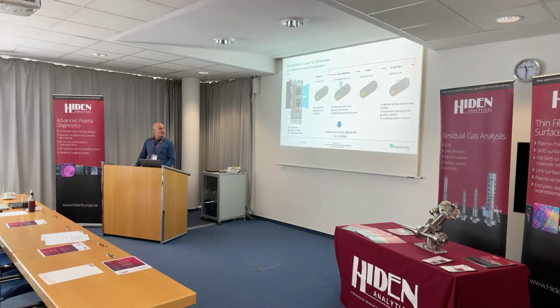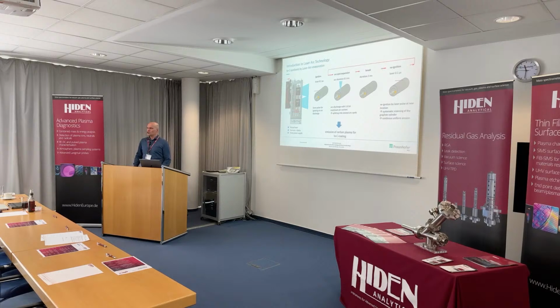So now let me introduce you to the laser arc technology. It's called LAM, and the M stands for modular. This was an initial idea to make it adaptable to any coating chamber, or nearly any coating chamber. This is what you see on the left. We have some graphite cathode material, and this is what we want to evaporate. And we are working with a pulsed laser. This is the first picture on the left.